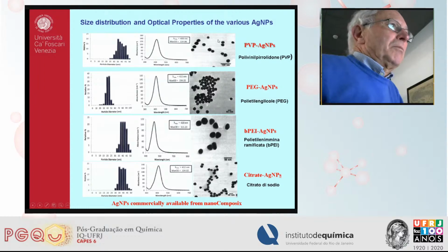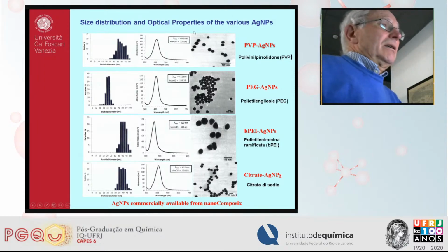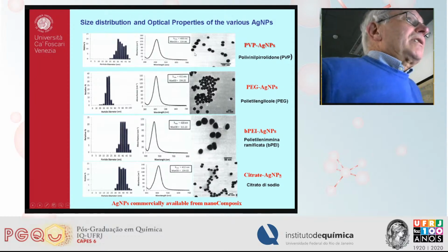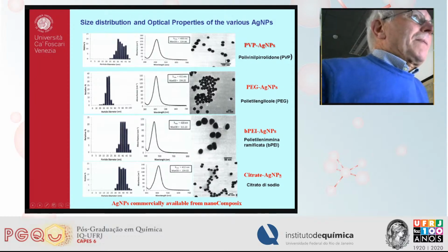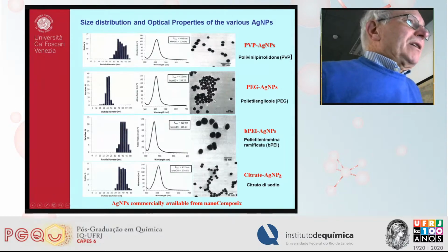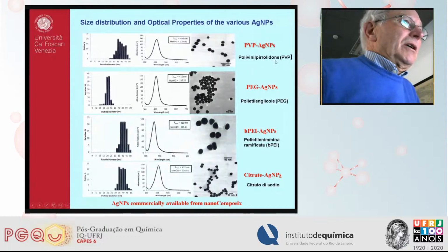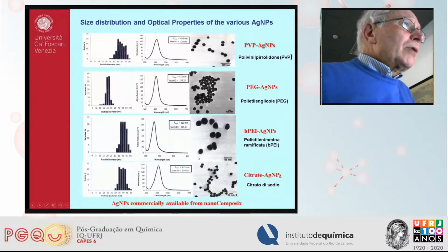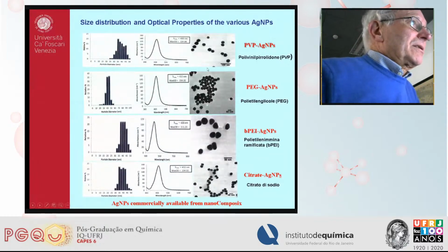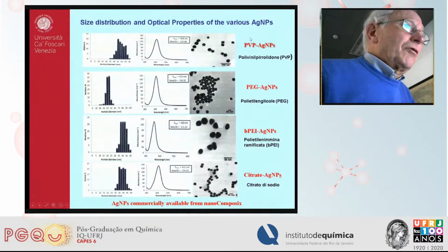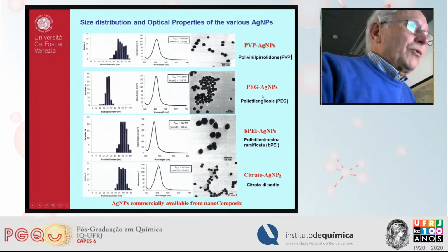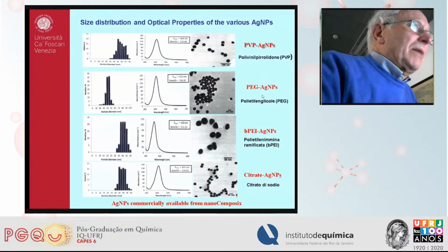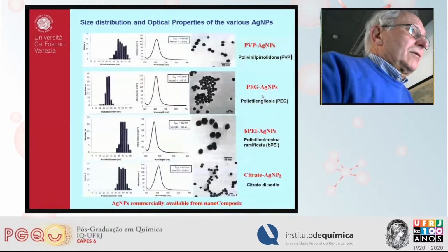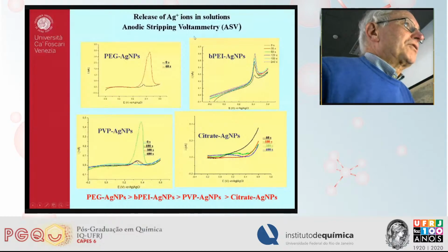Nanoparticles are formed from silver salts by reducing processes, by a chemical reductant in the presence, for instance, of some capping agent. And these are different types of nanoparticles coupled with PVP, PEG, and so on. More or less, they have the same shape and the same size. Anyway, the activity of these four types of nanoparticles is different. And we explored and detected the amount of silver ion released by using anodic stripping voltammetry.